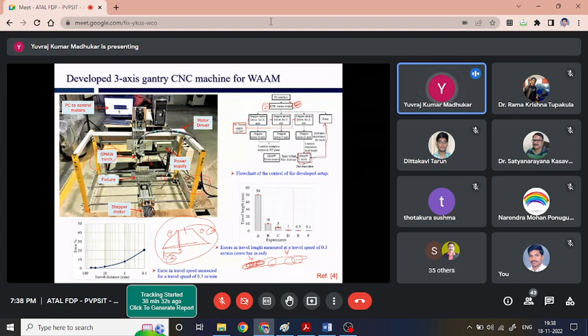Relay is nothing but an electrical switch which can be triggered with respect to a certain voltage, typically 0 to 5 volt DC or 0 to 10 volt DC. So whenever we get the G-code after slicing using any software, while loading that software into the PLC system, we have to write an additional line in order to trigger the relay. That relay is going to send the command to the GMAW torch to initiate or start the deposition process. So this part we have to do additionally to what we are getting from the result of a slicing process.